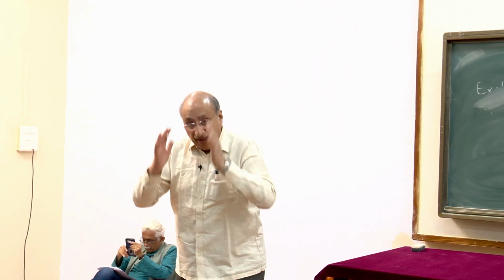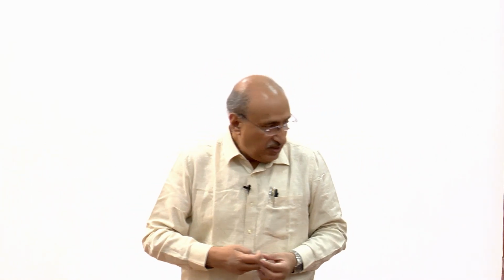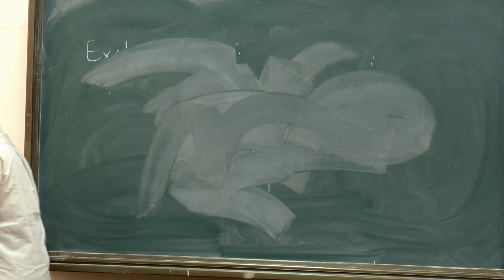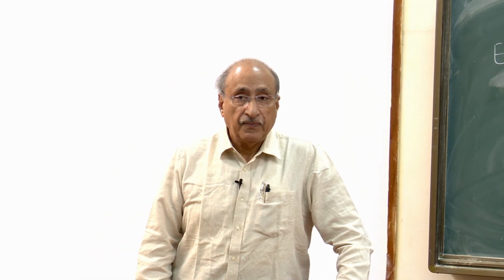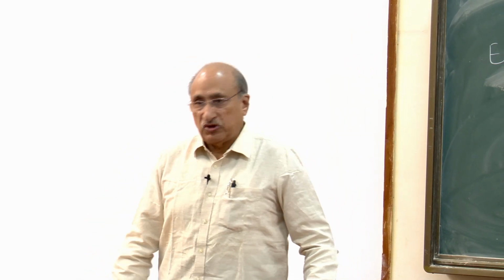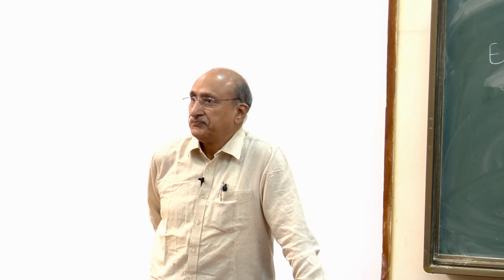And when you apply a field, then all these energies will get affected, and therefore a new domain structure will form, and that's how the mesh loop will be formed. That's what will decide what the mesh loop is going to be. Now let us suppose a case where anisotropy is dominant. Let's suppose it's a uniaxial anisotropy, which is generally seen in hexagonal structures. For example, cobalt shows a very large uniaxial anisotropy in the C direction.